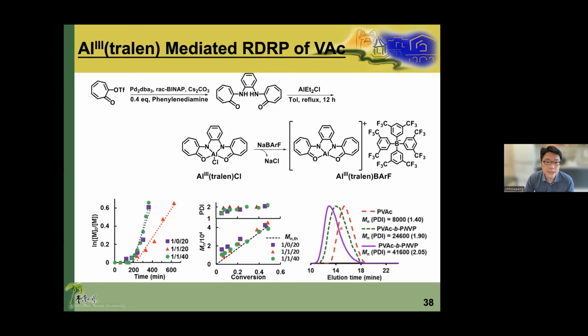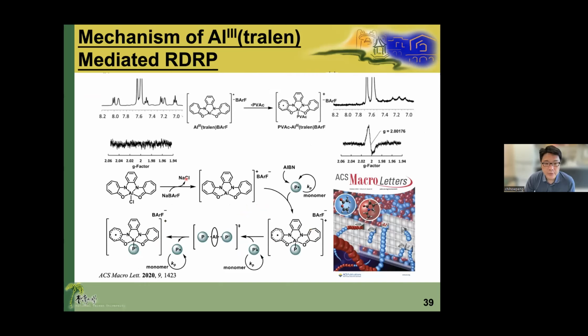We studied the mechanism and we understand the radical. Once you get the active species, the radical will be deactivated by aluminum and form a radical species, and we can observe this radical property, this 1 electron property by EPR spectrum. And then it can dissociate the radical by the chain transfer process, and we can mediate the vinyl acetate radical polymerization. So it was published in ACS Macro Letters.